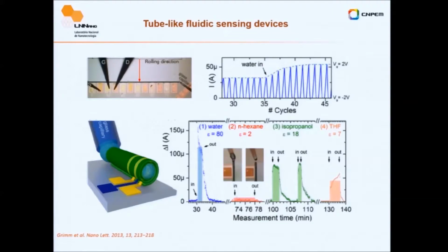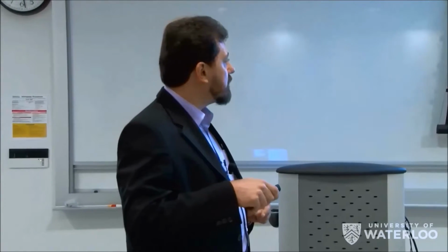We still don't know exactly which correlation this is, because it plays a lot on the surface, how it happens, what is going on at the surface. It's still an ongoing project. And what you see, depending on the dielectric constant, you can really increase or shrink the difference between these two gate voltages. And also, maybe if you force your eyes, you can see the curves get sharper or larger. So it means we are sensitive to the surface. And since you can roll it, we can also direct our fluid inside of the system.